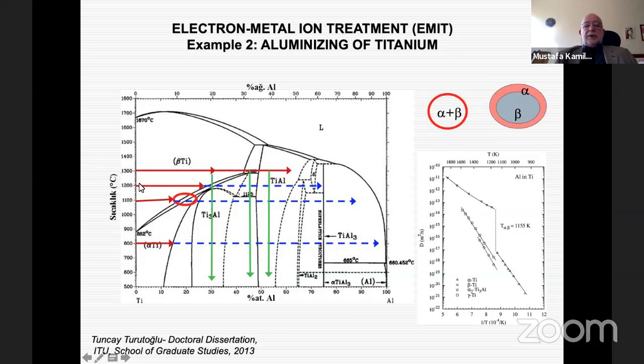When you conduct your tests under this region and cool down your samples, you end up with the formation of these phases. But when you try to go further, you end up coming to here. So when we look at 1300 degrees C, with a very high diffusion rate, we see that there is no limitation being imposed by alpha.